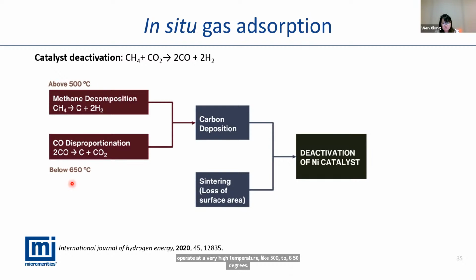At this high temperature, we can cause nickel deactivation, either by carbon deposition or sintering. If we want to check the deactivation of the nickel catalyst, we are able to see all the results or the reasons we mentioned here in one experiment by using the in-situ gas adsorption system. The in-situ gas adsorption system will help us check the deactivation mechanism more easily and quickly.